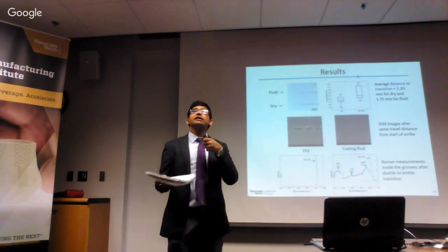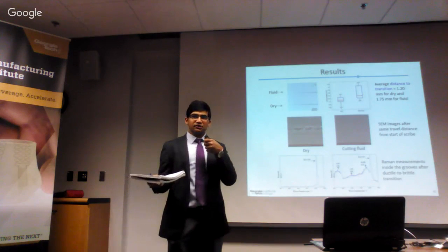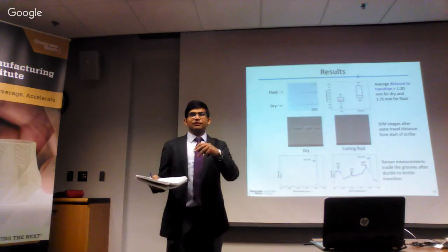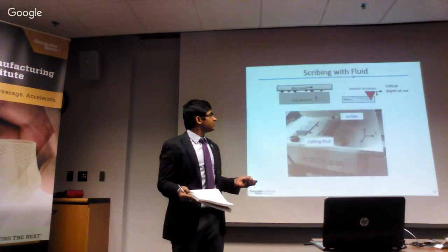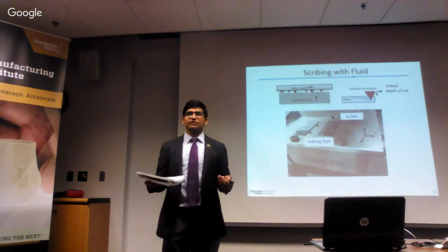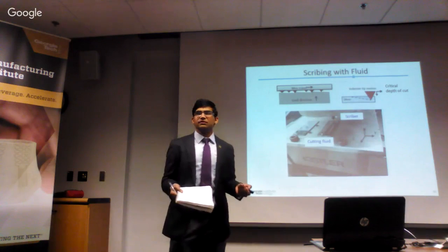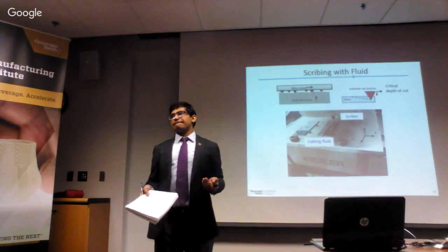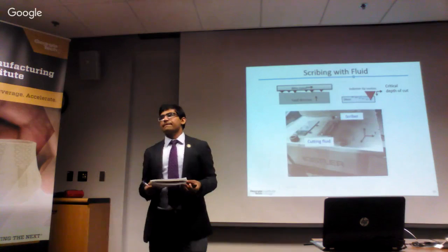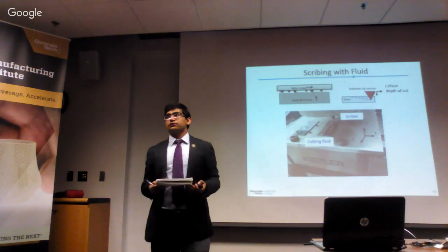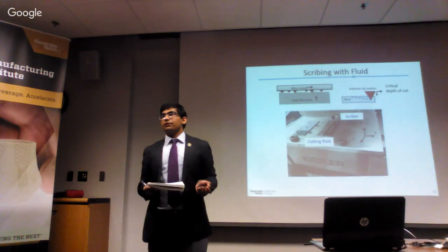Which means chemically there are some changes taking place. When you do that Vickers hardness, do you put the liquid on and just do the indent? You flood it? I flood it. I mean, this was the scribing, but in Vickers also you flood it. Is there a difference in the depth of the indent with and without the fluid?